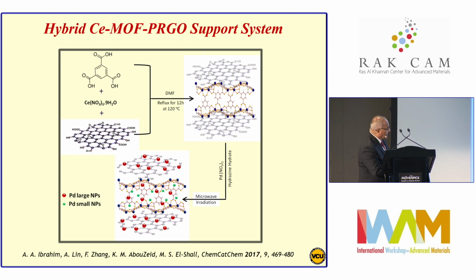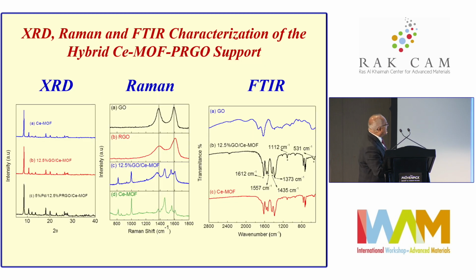Here, by reduction, you can typically use microwave reduction for this process. So we end up incorporating palladium nanoparticles within the MOF and also within the reduced graphene oxide below and above the MOF crystal structure. Of course, there is some characterization here.